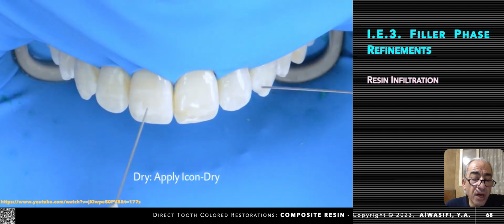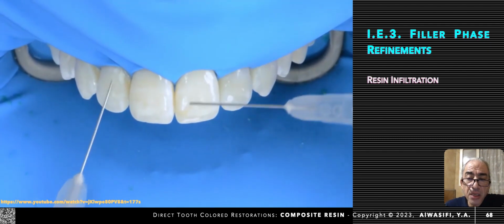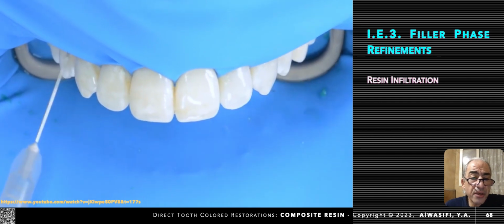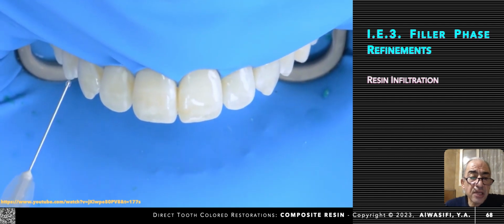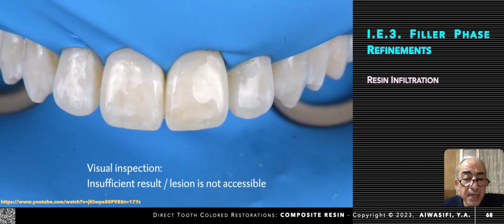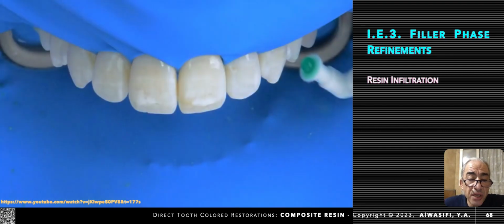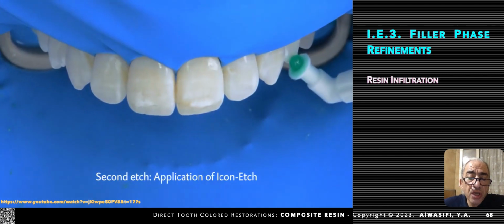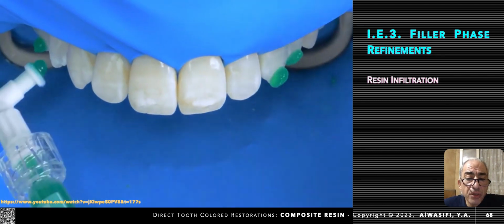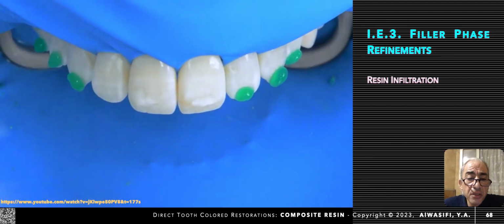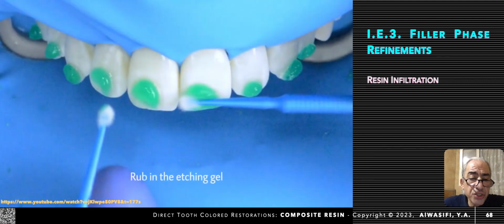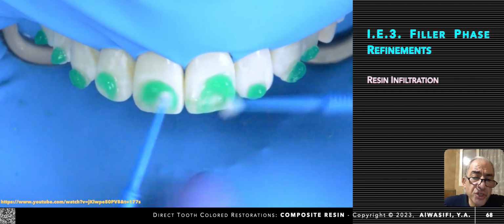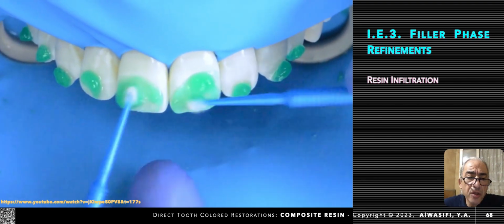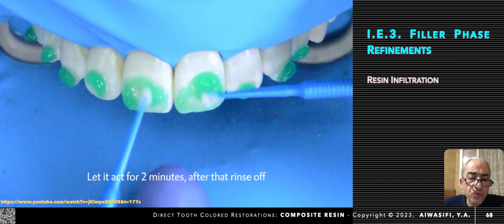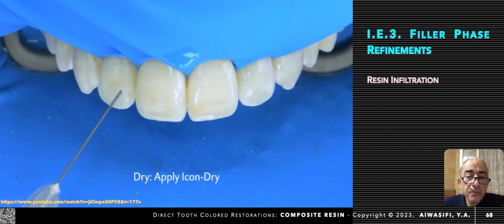Apply the dryer, which is 99% ethanol, that will evaporate water, for 30 seconds. Then do a visual inspection to see if the etching is sufficient or not, according to the chalky white appearance of your surface. Re-etch, re-rub the gel, 30 seconds maximum for each tooth, and the total amount of etching is 2 minutes.